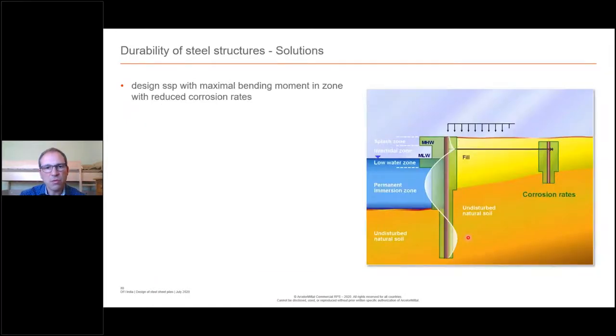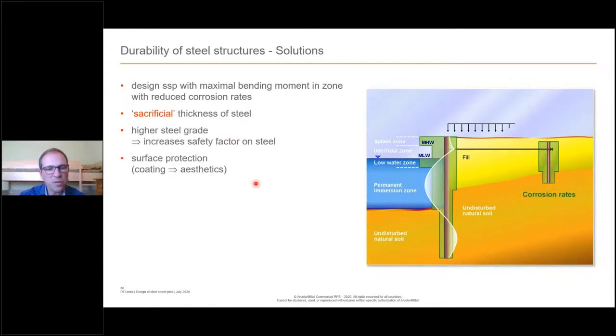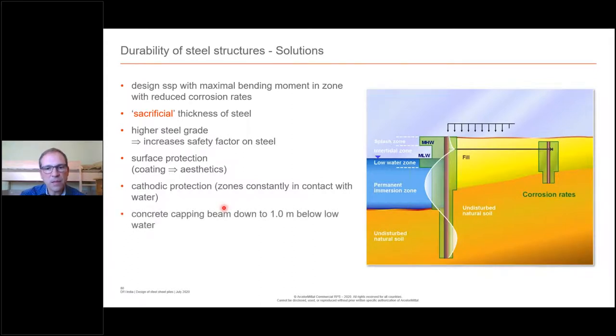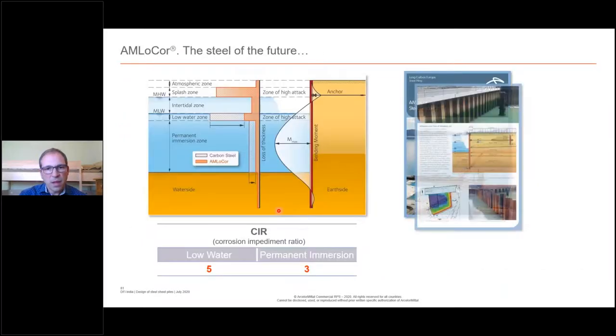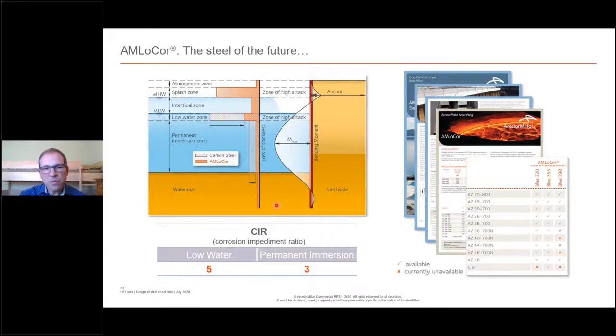Now, if you look at the different ways to deal with it, there are different solutions. You can increase the thickness, you can increase the steel grade, you can protect the steel, you can use cathodic protection, which works very well in the water, and you can also use a capping beam down to -1, so that you will protect the most corroded portion with the concrete. There's also this AMLoCor, which is more corrosion resistant in the permanent immersion zone and in the low water zone. It reduces corrosion by a factor of 5 or a factor of 3, but it's only available for specific sheet piles like the AZ sections here.